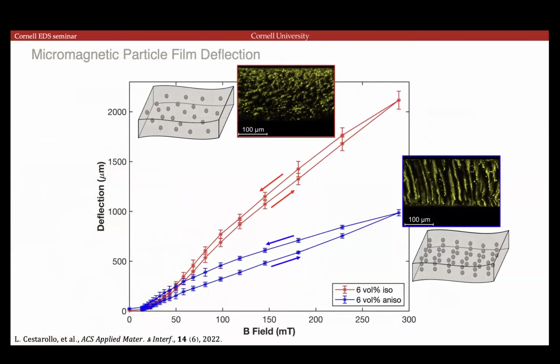And it's very clear that one of the two wins out. This is for films with just 6% by volume of magnetic particles in the film. And we already get out of a 200 micron thick film millimeter scale deflection. So 2000 microns is just 2 millimeters deflection at fairly low fields. What we're interested in is actually these fields that are 100 millitesla or below that are fairly easy to apply within an electronic system.